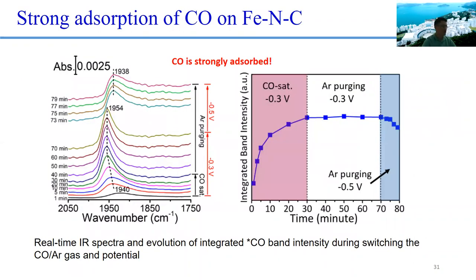But the problem here is that this CO adsorption on iron is very, very strong. For example, we did this experiment. First, we adsorbed the CO at minus 0.3 volt. CO is strongly adsorbed on the catalyst, and then it saturated. So you can see the signal of the CO increase and then stabilize.